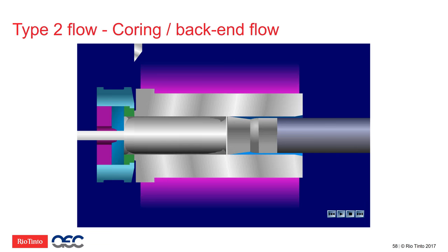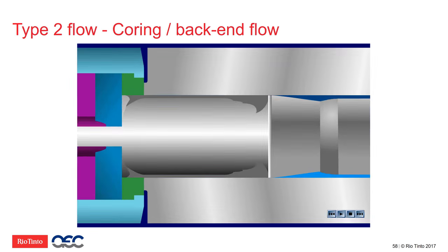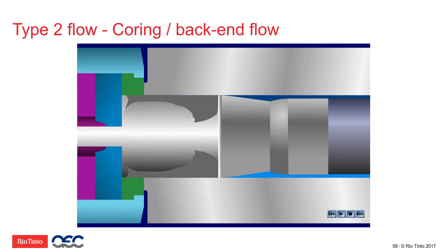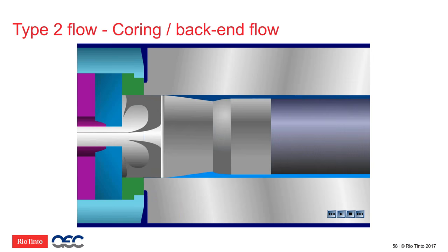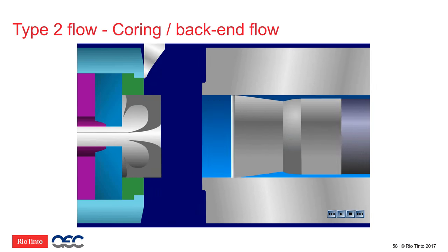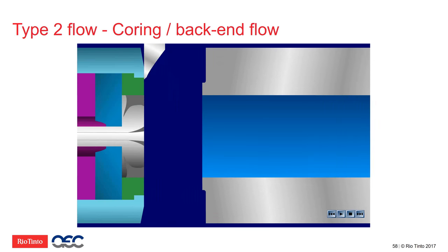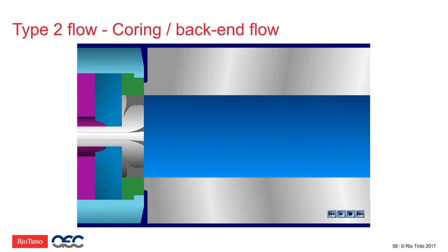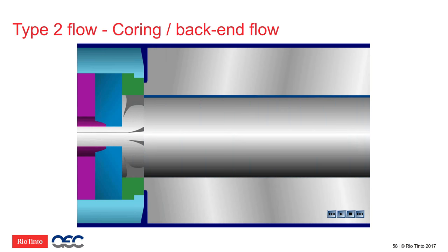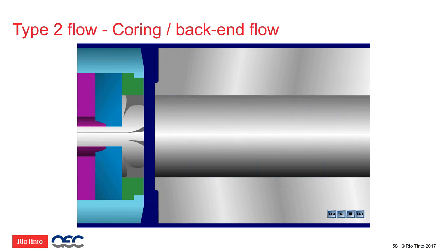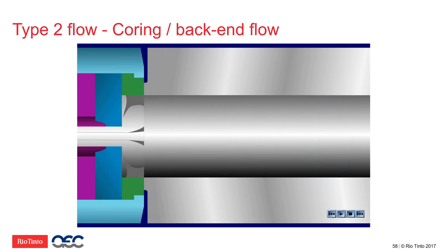You've seen those now quite a bit, but you will see the accumulation of the billet skin facing the dummy block, and then as the extrusion progresses near the die, the coring starts working. So the shear takes place, the butt is removed, but as you can see, there is still some coring trapped inside the die, okay? So the new billet gets loaded, upset, and we start pushing.